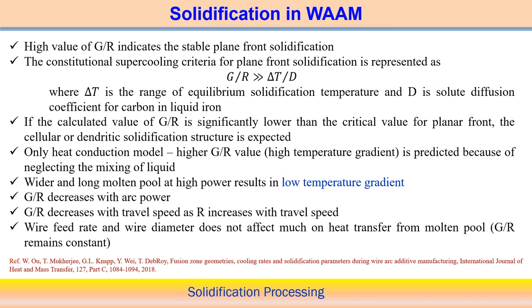In wire arc additive manufacturing, solidification behavior is also indicated by the G/R ratio. A very high G/R ratio means the temperature gradient G is much greater relative to the growth rate R, and the planar front will be more stable.